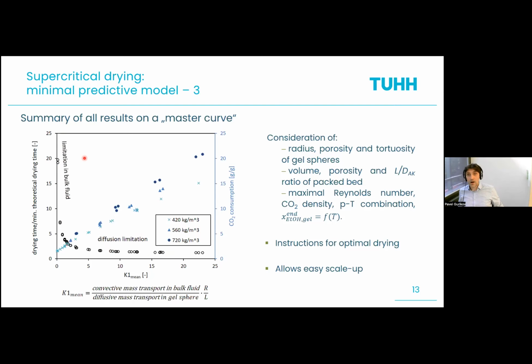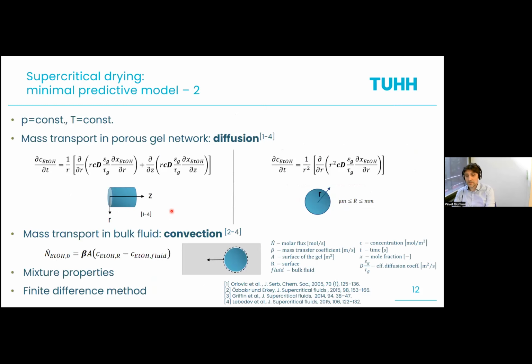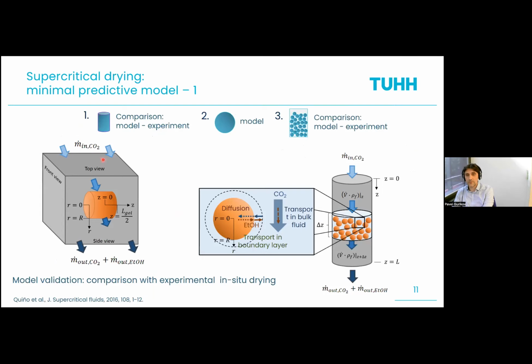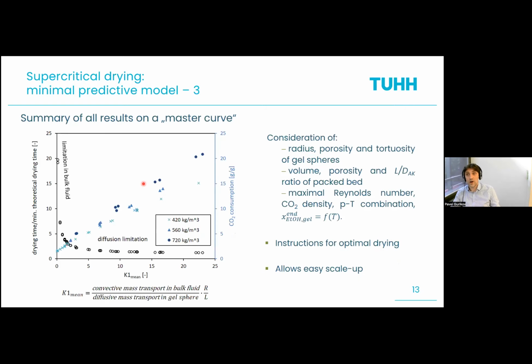Second thing you may ask, how much CO2 do I consume in all these cases? And this model gives you, of course, a very natural answer, because you always have the mass transfer, the flow rate of CO2, and then you can easily recalculate how much CO2 you have to introduce into the equipment. And with this data, you can begin what we first call instructions, or just playing with the model to see what happens if I change this and that parameter, what happens if I change temperature, pressure, size, and all of them.